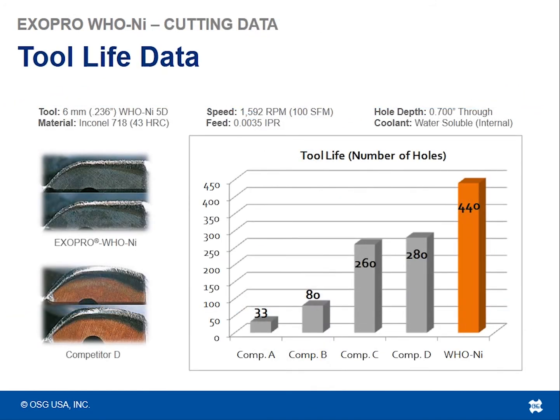Here I'm showing you a little bit of tool life data on the WhoNi 5xD. It's a 6mm tool in Inconel 718, which was hardened to 43 Rockwell. We're doing about 100 surface feet, so about 1500, 1600 RPM with 3.5 thou inches per revolution. This is a through hole 700 thousandths deep with coolant through. So we're looking at the number of holes that these tools were able to get. You see we've got 4 different competitors and the WhoNi drill, as well as how many holes in these conditions they were able to get.